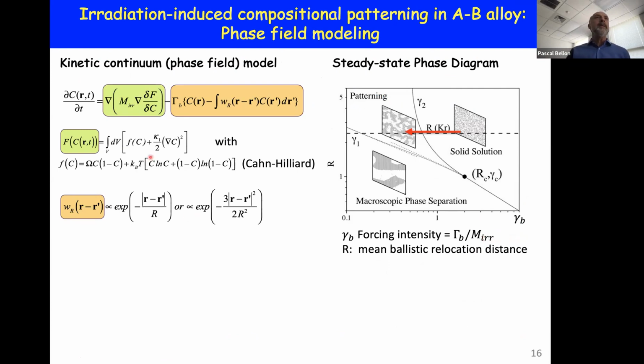So I mentioned briefly that we use phase field modeling to build this phase diagram that I showed you previously. This phase field model is captured here by a kinetic equation that controls the evolution of one concentration field. We're in a binary alloy. So C is the concentration, say, of the B species.